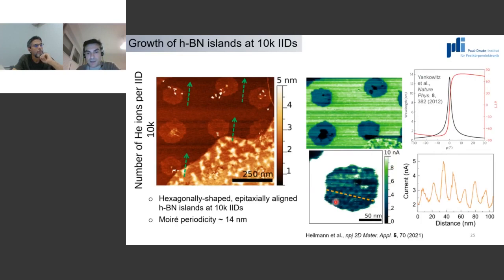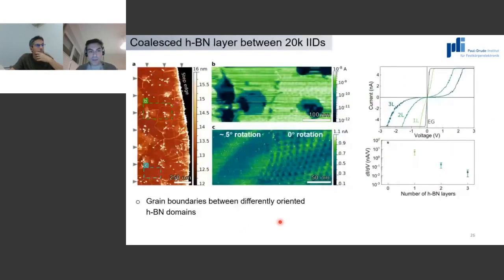And if we now consider this island here and we have a look at the periodicity of this moire pattern, this corresponds to the most stable epitaxial alignment between graphene and HBN that would be 0 degrees, as calculated and shown in this paper, and this gives you a moire periodicity of about 14 nanometers. But the takeaway message here is that this confirms that this defect-mediated van der Waals epitaxy is taking place, and that you can use defect engineering on your 2D template to modulate this epitaxial growth. Just going on here,